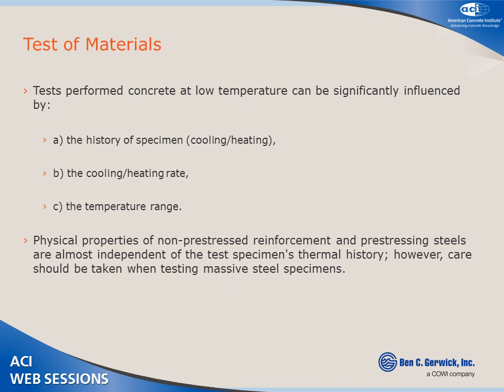Tests performed at low temperatures can significantly influence properties. That said, most of the properties of concrete are generally controlled at ambient temperature. Concrete tends to improve in strength, and most engineering properties are improved at cryogenic temperatures — it's already brittle, so it already depends on steel pre-stressing or reinforcement for ductility. Most concrete properties controlling design are frequently controlled at ambient temperature, when pre-stressing operations can proof-load the concrete before you get to low temperature.